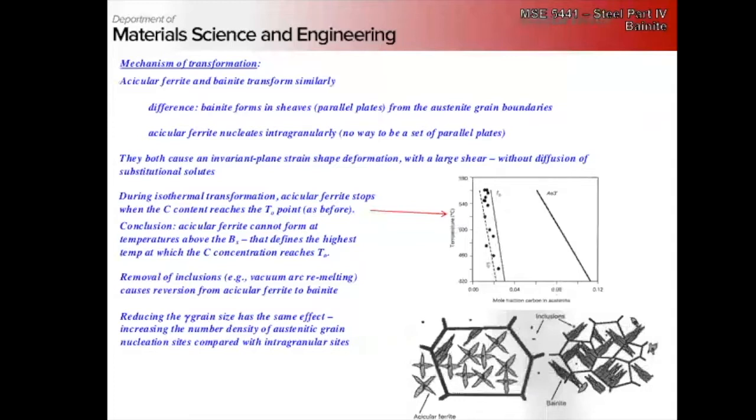If we have small grains, right, a lot more surface area, right? Remember, surface area goes by what with respect to the radius? Right, squares, right? And so we're making the grains a little bit smaller, which gives you a drastic increase in surface area, a lot more nucleation sites. So if we make our austenite grains smaller, we eliminate acicular ferrite.